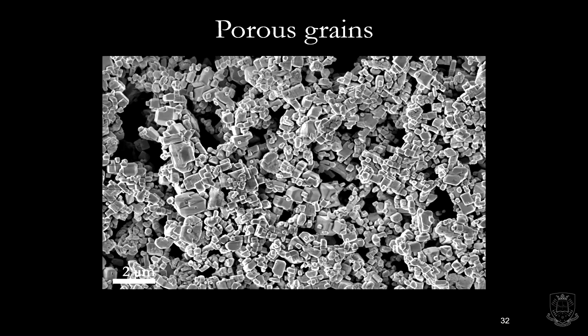But this is how it looks like in SEM. So then we are in scanning electron microscopy, again, larger scales. I could also see with different techniques that they had a very porous structure. So the porosity of the crystals can also be useful, maybe not for a solar cell, but if we think about other interactions where you want to have a large surface. And because of the good conductivity in the material and so on, maybe the properties can be used in other techniques as well.